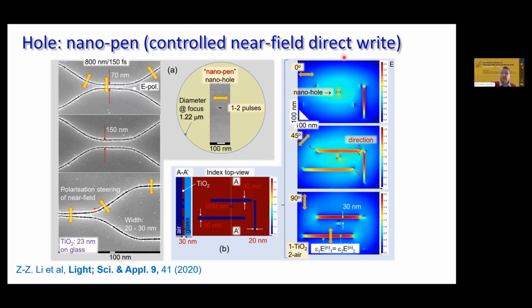So let's have a look at what happens to the enhancement of electrical field for different polarizations. For horizontal, you don't see those horizontal grooves, but you see very nicely that light is localized inside the groove which is vertical. If you have 45 degrees, you have slightly smaller concentration of light in that vertical groove, but also you begin to see those horizontal ones. If you see the dot, light is also concentrated inside, but you see some depression of intensity nearby. And this is the reason why you can write nanostructures very closely. Let's look at this vertical polarization, 90 degrees.